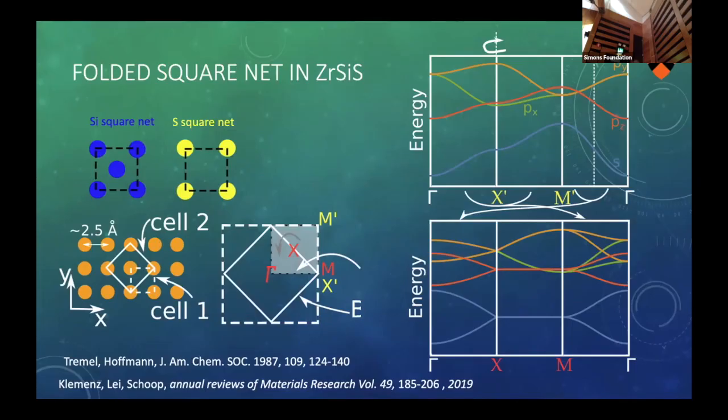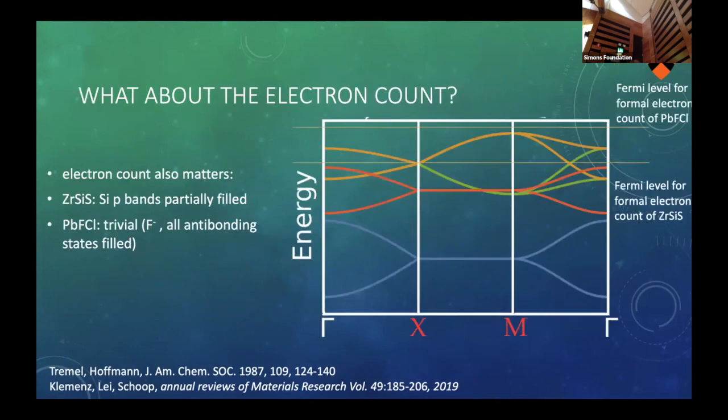So why do I care about chemical bonding? What band folding does is create these crossings, or these points at the Brillouin zone boundaries, as has been discussed by Young and Kane and other people, but it does not put my Fermi level in the right place. If I just have 2 atoms per unit cell, my Fermi level could be up here, down there, or over there, who knows where. But if I combine this with the electron count condition for a chemically delocalized, hypervalent bond, then my Fermi level will automatically be pinned at the position where the band crossing is.